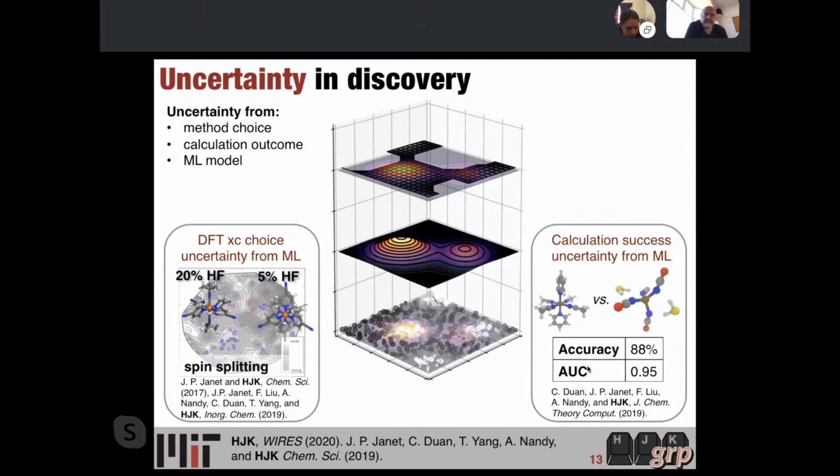And then the other question is about diversity. The tricky thing we do is we always do metal oxidation state 2 or higher. The reason we do that is because in the first row that eliminates s electrons being what determines the spin state. So we're always talking about d to d transitions. We typically look at the accessible spin states from something like the NIST database. And so what this means is for the mid row, we have low spin and high spin, which differ by 4 electrons unpairing, in oxidation states 2 and 3.